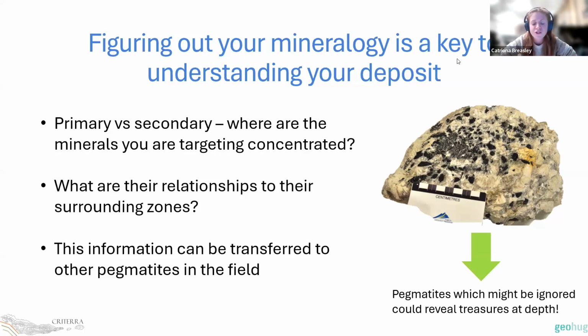Finding out these mineralogical relationships in the different zones within your pegmatite is also important because there can be some reoccurring relationships, such as the presence of two zones that are always beside each other and coexisting. And at the end of the day, this early stage information and finding out your paragenetic sequence is information that can be transferred into the field where often pegmatites are geochemically linked and similar trends can be seen. And also, back to this rock again from Revelstoke, pegmatites, which might usually be ignored on the surface, which could look barren, can reveal treasures at depth.